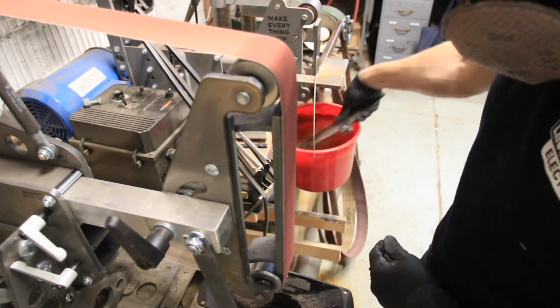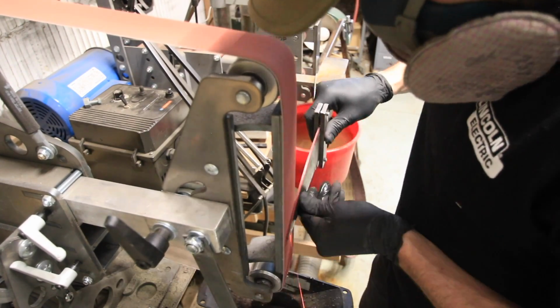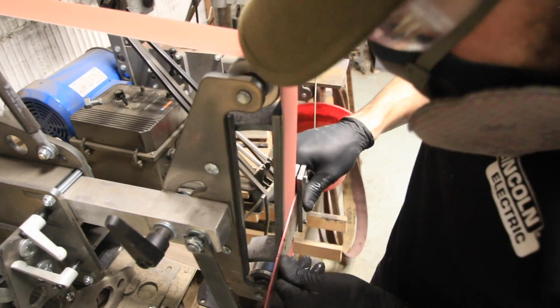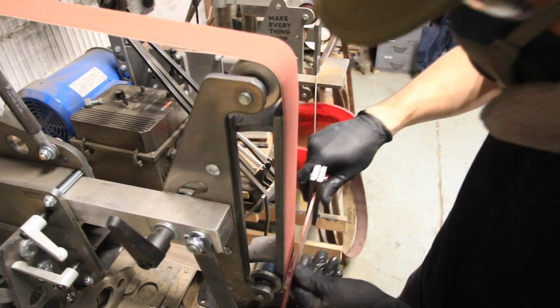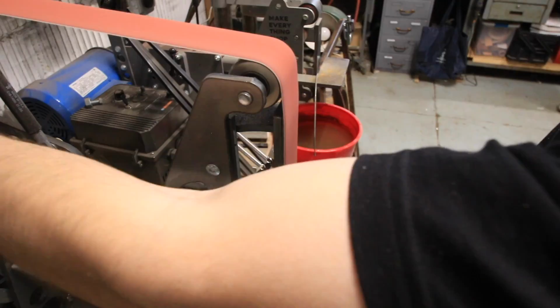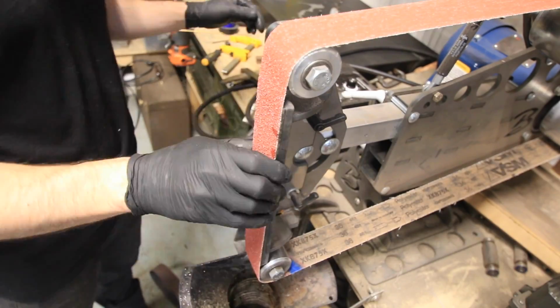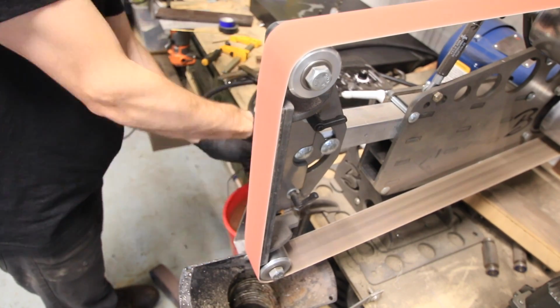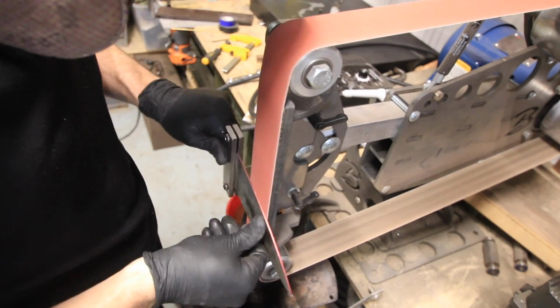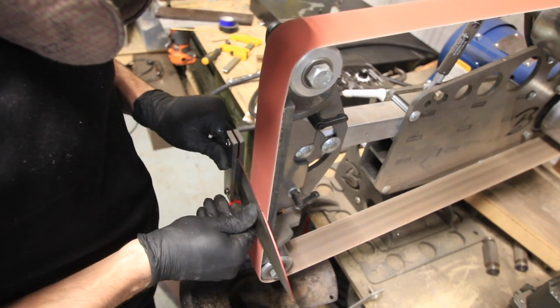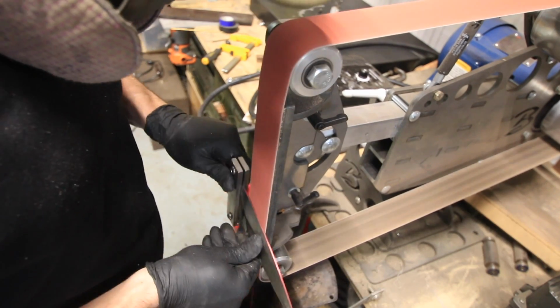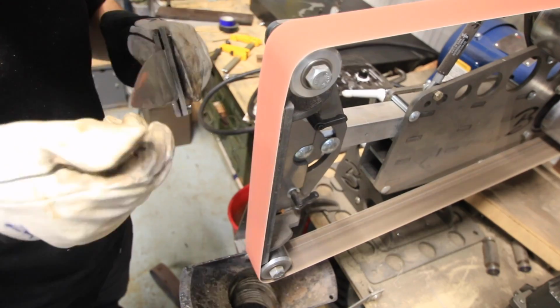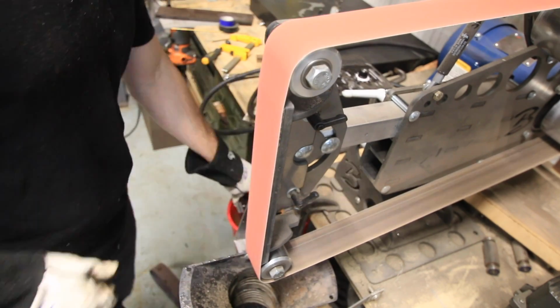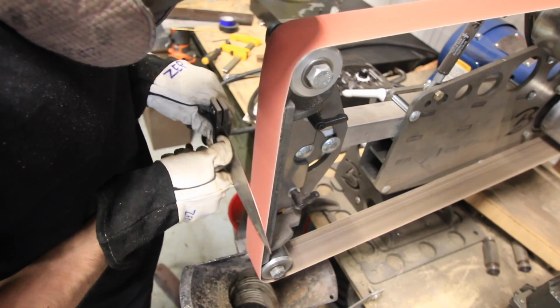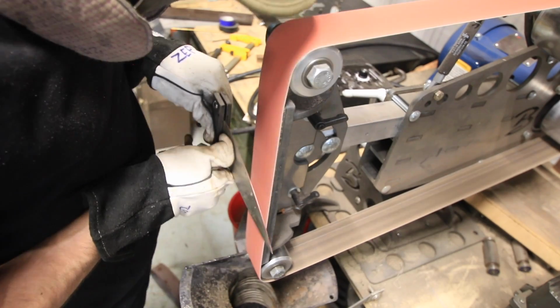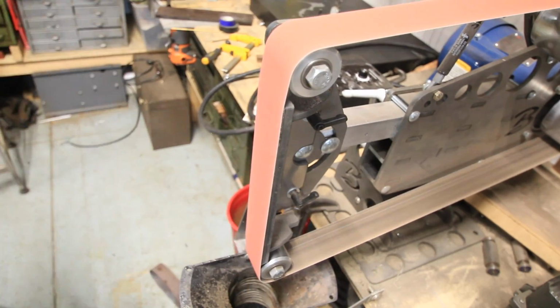And what's nice about some of these belts, like this is a structured abrasive belt, so you're getting a lot less fine grinding dust, and you're almost getting like grinding chips. You get these long strands of metal coming off the belt, and it really goes through the metal efficiently. The blade stays nice and cool. I'm conscious to dunk it in water very often, because remember, this thing is heat treated and tempered, so I don't want to ruin that temper. The last thing I want to do is see any coloration on the blade, because that'll tell me that I ruined the temper that I just spent 4 hours on.